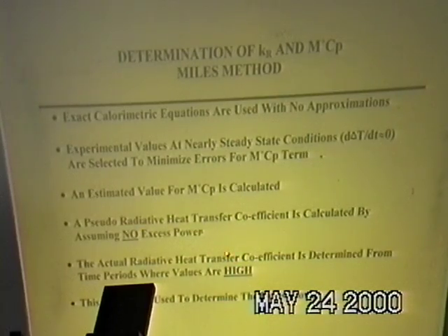I determined a pseudo-radiative heat transfer coefficient by assuming there's no excess heat. And then I found periods where these heat transfer coefficients, assuming no excess heat, are high. Those would be periods where the excess heat was low, because excess heat will make your heat transfer coefficient go down if you assume there's no excess power. So I calculated the heat transfer coefficient and then used periods where it was high, where therefore the excess heat would be small or zero, and used that for my heat transfer coefficient as an approximation. And then I used this value going back into the equation to calculate what the excess power would be.